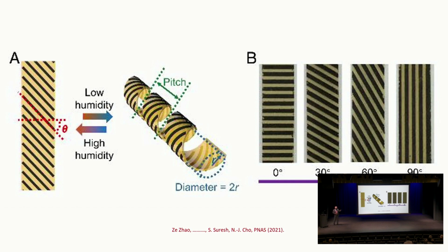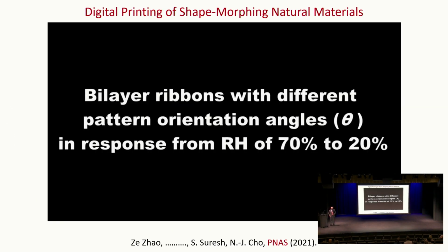Now, as engineers, we can go to town with it. We can take plant material, and we can do a number of things with it. So the first thing I want to show you is a video of what happens when you take the strip of pollen paper, which has lines patterned on it. We're going to start with 0 degrees, go to 30, 60, and 90 degrees. We change the moisture. We go from high humidity to low humidity and back to high humidity. See what happens.